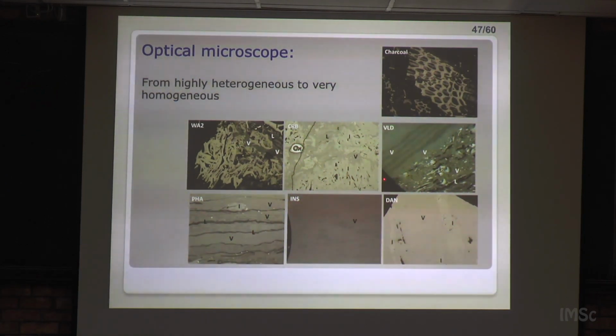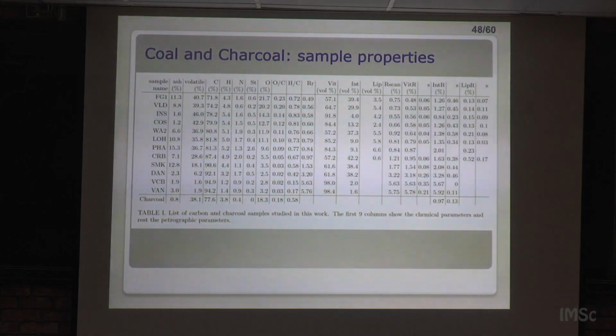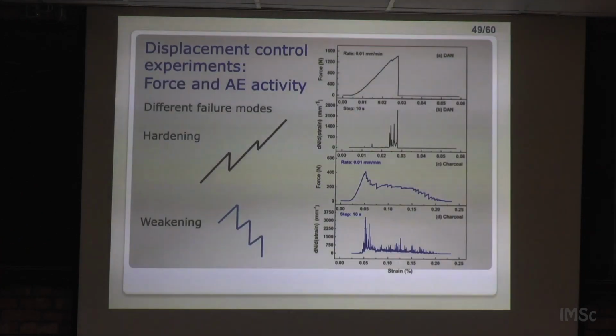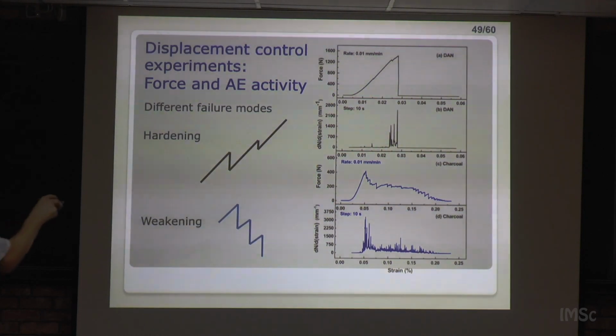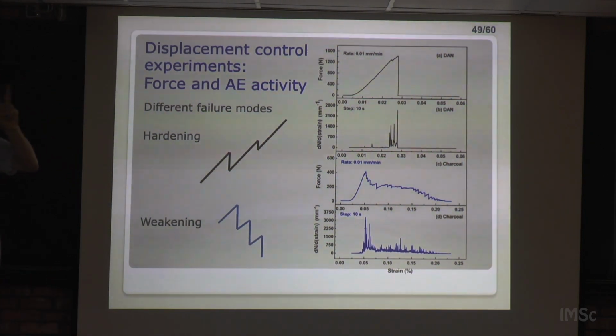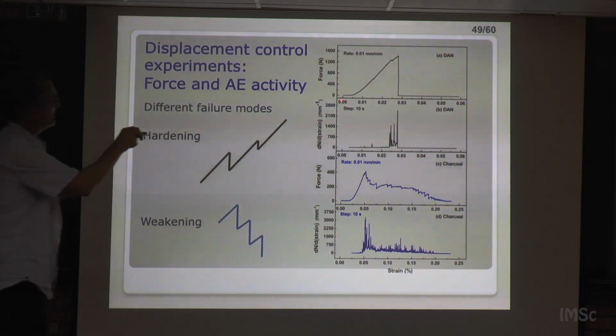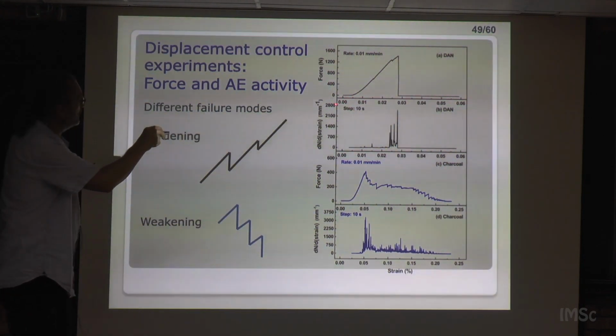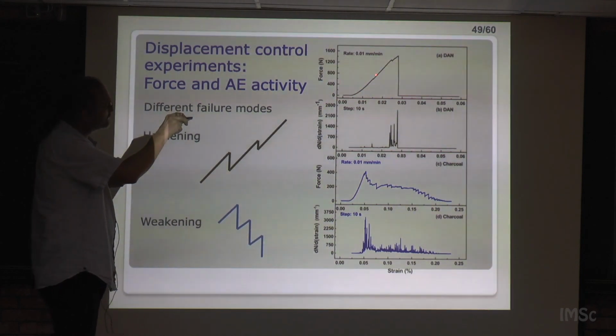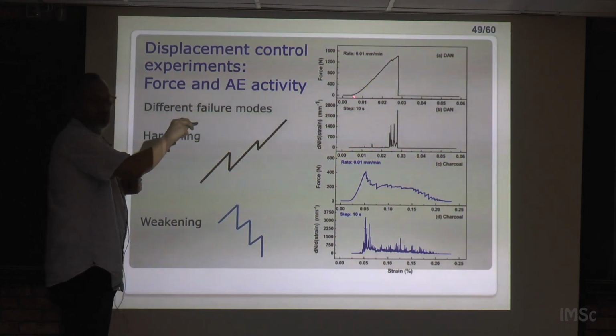But this is, let's say, the most heterogeneous one, and we go down to the, okay, I go very fast now. So we have this gradation of samples. These samples can be studied very well with composition, etc. But we can order them from very heterogeneous to more homogeneous by different methods. Essentially, and now is your answer to your problem here, we can classify, you will see there are two kinds of behavior. In this case here, you see force against strain, okay? You have this elastic part, and then it starts to fail, and then there is a brittle failure, pam.